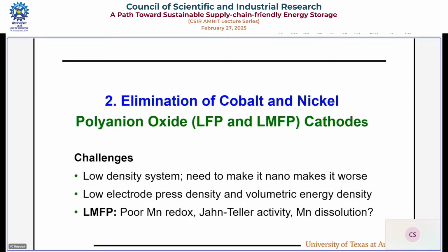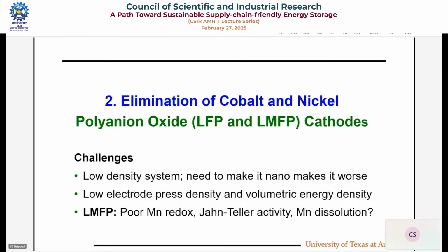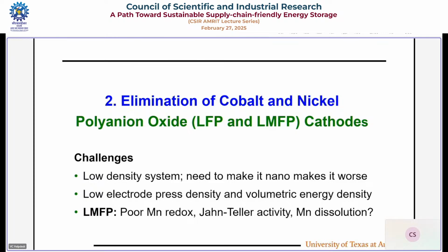For all applications, volumetric energy density is much more important than gravimetric energy density. For a car, space is more critical. Yes, weight is important, but they are not too worried. But this system is pretty bad for volumetric energy density because it is nano and porous. This is even worse. When you have manganese, there is poor manganese redox kinetics, and it can also undergo Jahn-Teller activity, which can lead to dissolution.